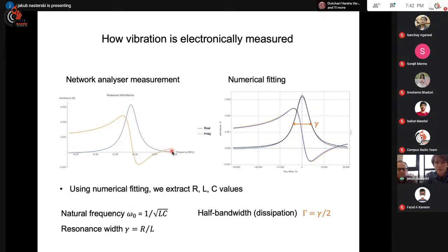And what we do is we can fit this curve numerically. Numerically, we can simply extract the RLC values corresponding to this curve. And when we have the RLC values, we simply calculate the natural frequency and the gamma. So just to summarize those last 3 or 4 slides, if you were a bit lost, that's all you need to know for the next part. And also an important thing to note, this gamma, which is R over L, corresponds to the width of the resonance peak at half of the power.